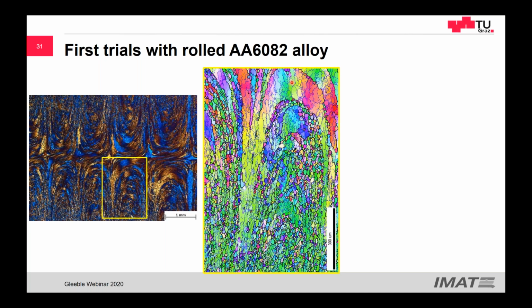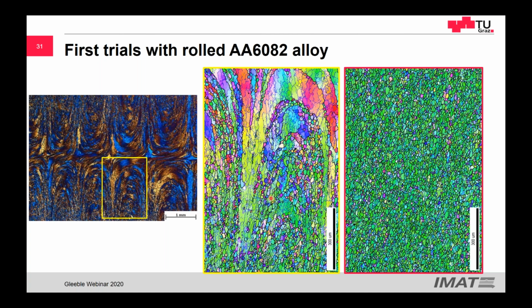We have some grains close to the center of the sample that have much less deformation, and with this you can see the formation of subgrains, so the blue lines are the subgrains. But still we had, and this is taken from the border, very, very refined grains. So first we proved that indeed there is some refinement of the grains. We also proved that this happens continuously, but we couldn't get very good statistical results.